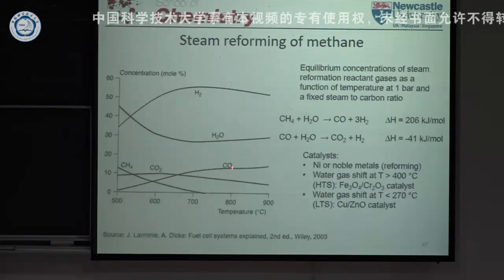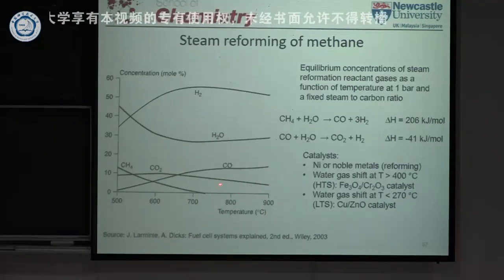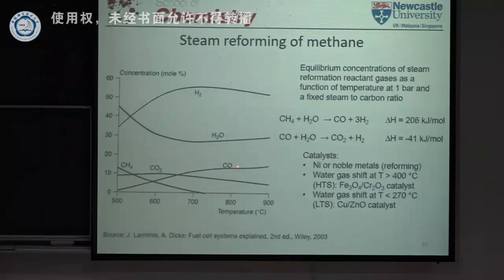And then you look at these concentrations, and at 800 you see you have a considerable amount of CO here. It's above 10%, maybe 14%. Then you have water, and here's the hydrogen, and this is the CO2. So depending on the application, when you want to feed this into a fuel cell, the first thing you need to do is remove all this carbon monoxide, because carbon monoxide is a poison for the catalyst, and having 12% is not very good. So what you need to do is reduce this to a few ppm, an enormous task.